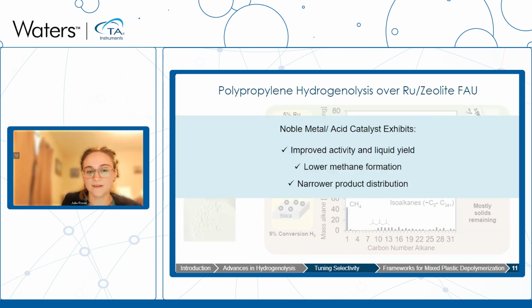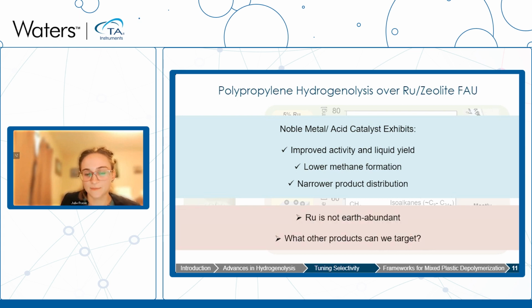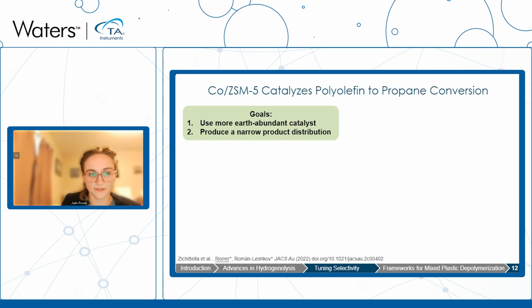And so this bifunctional noble metal acid catalyst exhibits improved activity in liquid yield, lower rates of methane formation, and a narrower product distribution. But we still have a few challenges. One is that ruthenium is an expensive and not earth-abundant material. And 2, we're still producing a distribution of products. What if we could target a single product that could be used to make new polymers and impart circularity into the process? So we sought out to do those 2 things, use a more earth-abundant catalyst and produce a narrower product distribution.